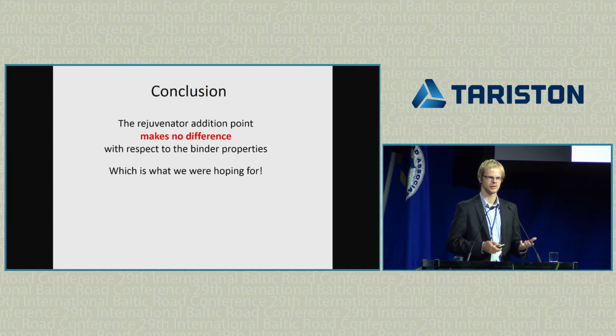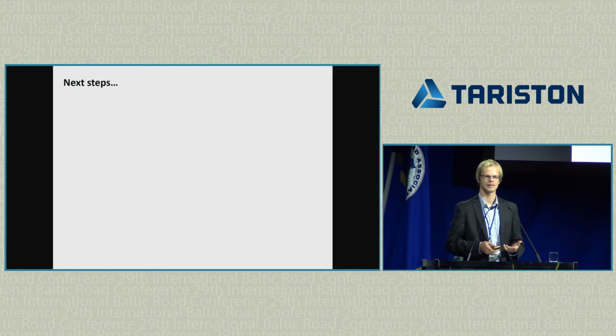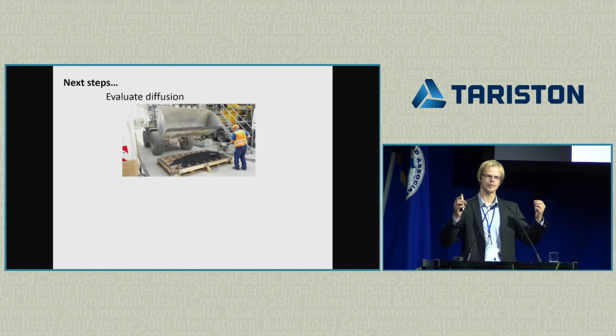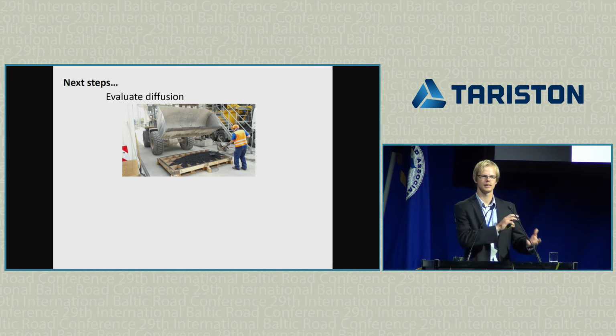Whether it's better, I cannot answer at the moment because we haven't done any testing on the mixture. As I said, when we extract the binder, we blend all the materials together. So in this case, we artificially assume 100% blending, which is not what happens in the real world. In the real world, there is probably a little bit less blending, and we have to find that out by testing asphalt mixture. That is what we intend to do. We have already gathered samples, and we will perform the testing on asphalt mixtures.